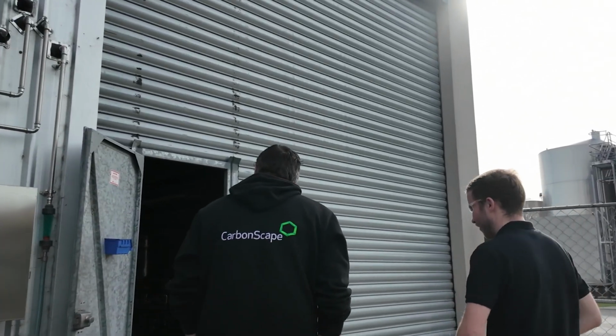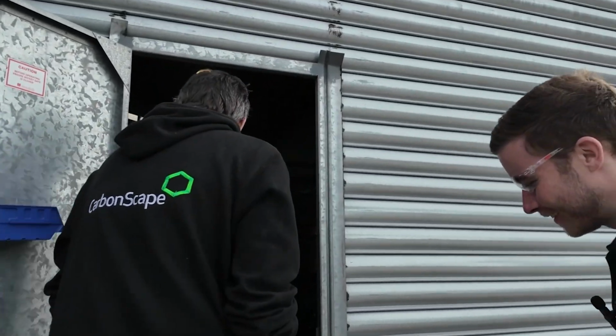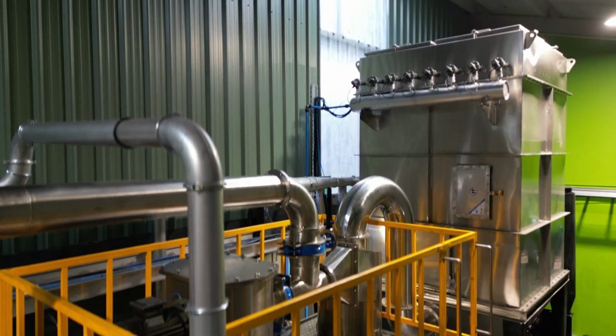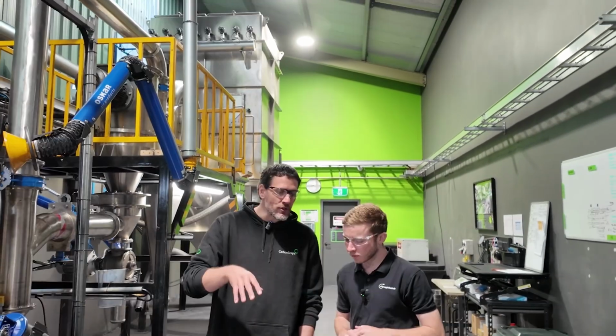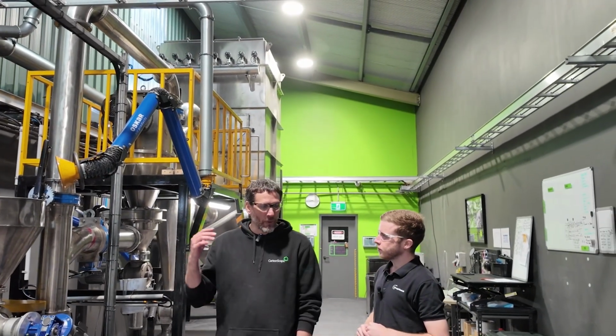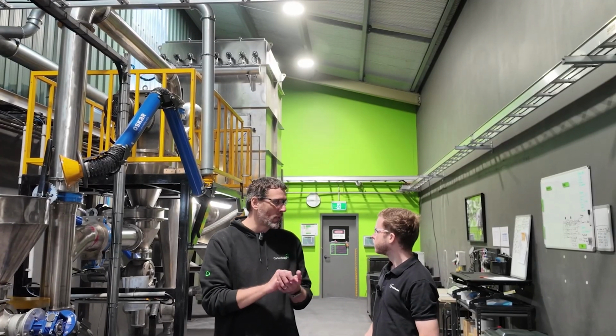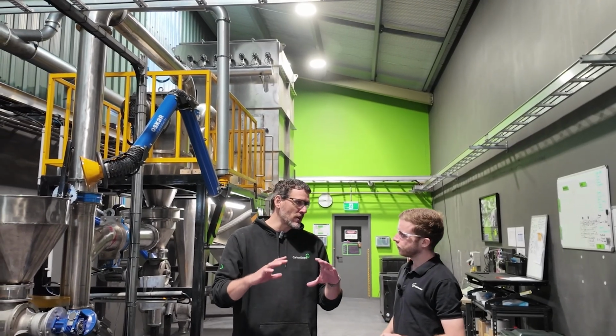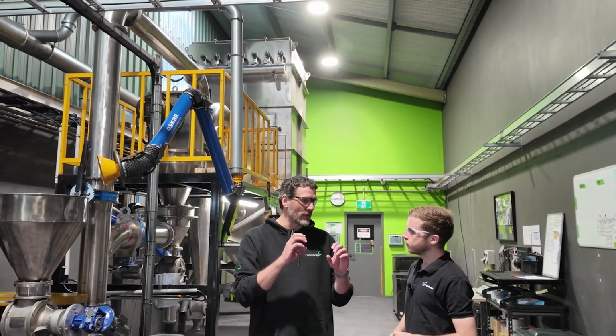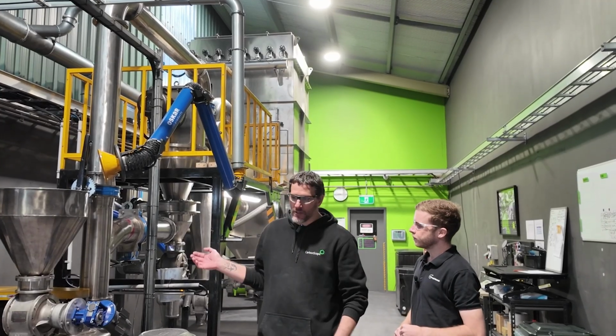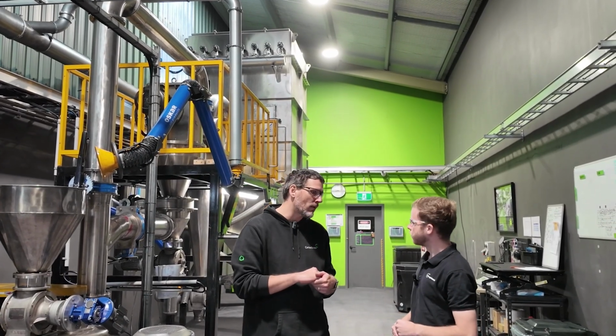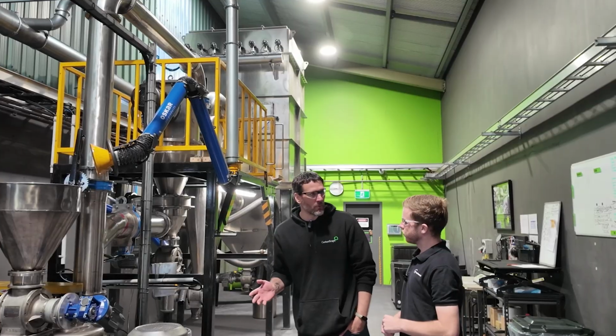With purification complete, the material is now ready for spheronisation. It's called spheronisation. So one of the key factors in getting the graphite anode performance is you want to increase its tap density, which increases the energy density of the final battery. And so what we do here is we're essentially shaping the particles, because the most efficient packing that you can achieve is if it's spheres that pack. And so this is like smoothing and rounding the particles so that we can achieve the best possible energy density.